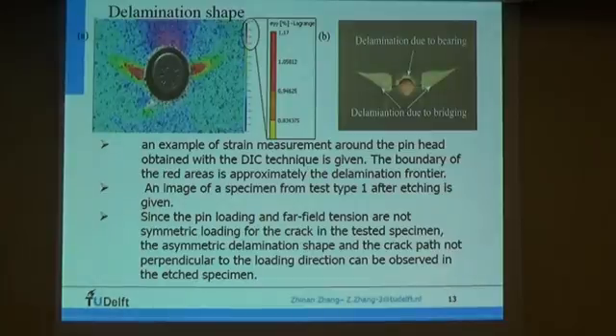And secondly, the delamination shape. The left picture is an example of the strain measurements around the pin head, often with the DIC system. The boundary of the red area we can see here and here is approximately the delamination front. And the right picture is a measurement of a specimen from the test type 1 after etching.